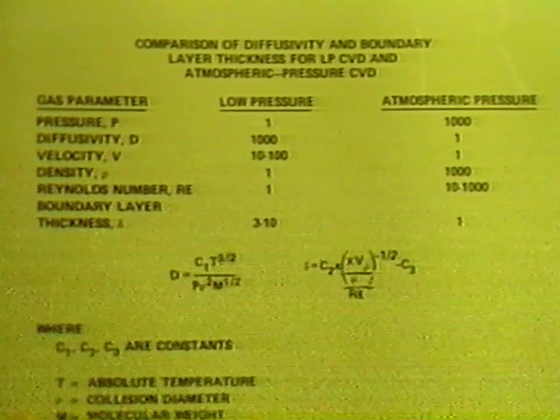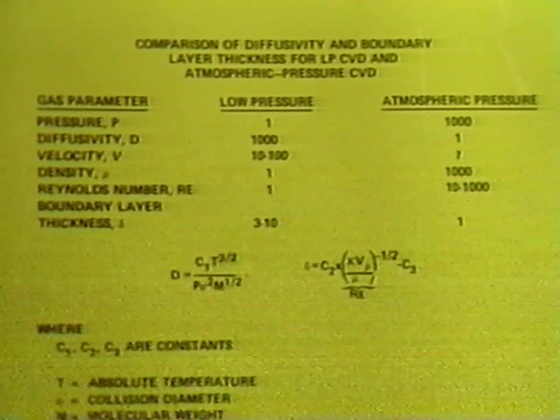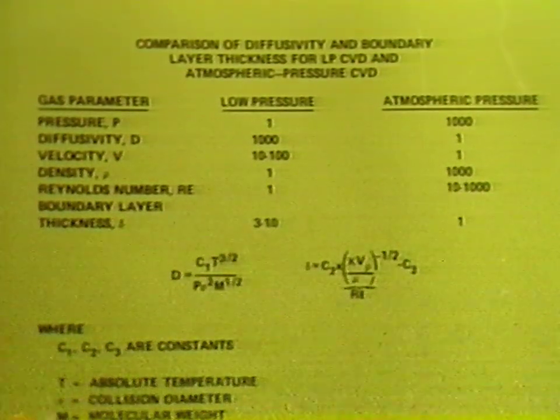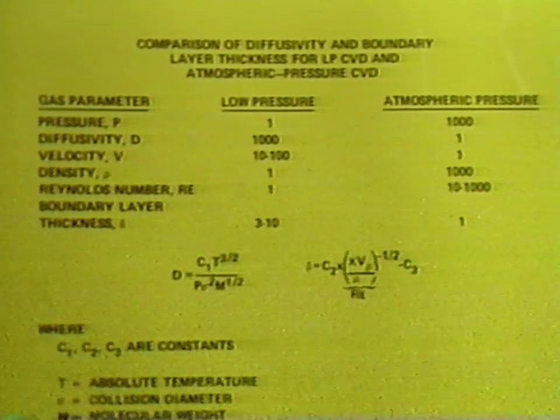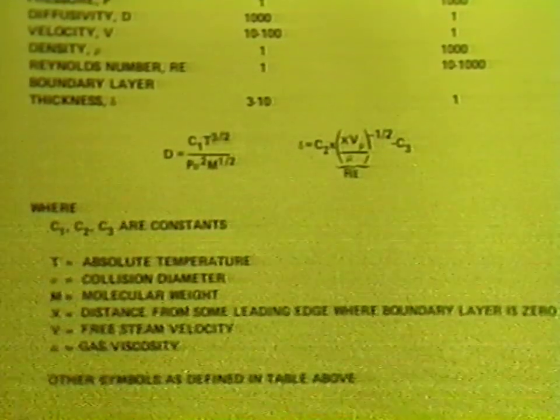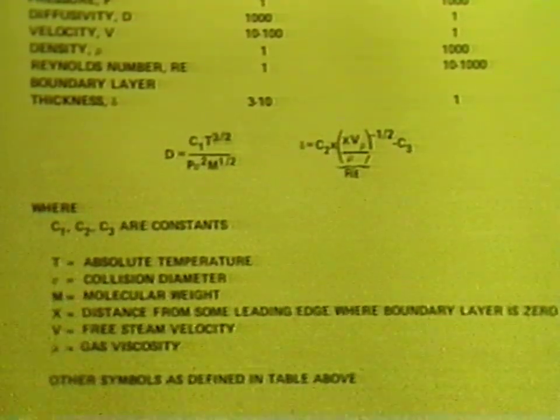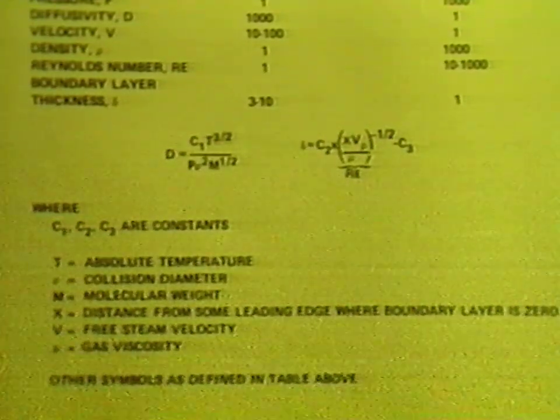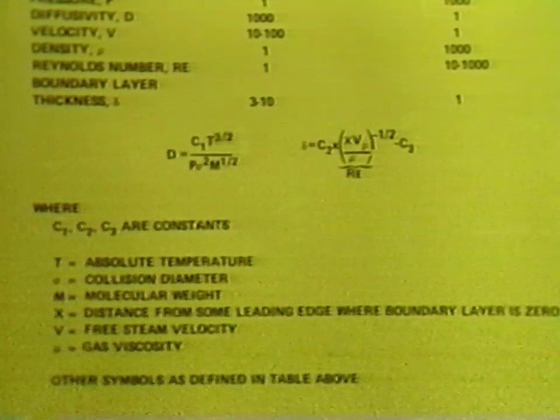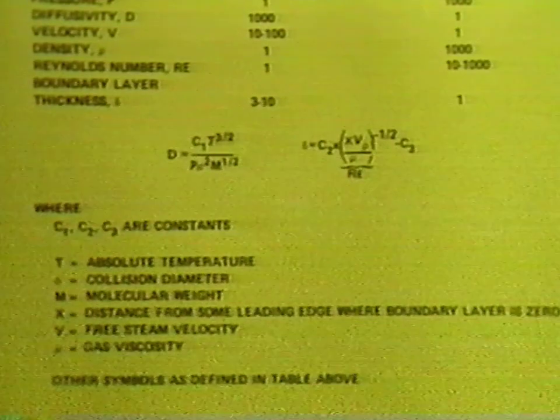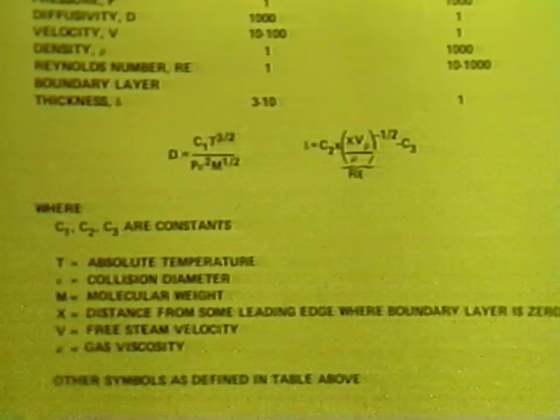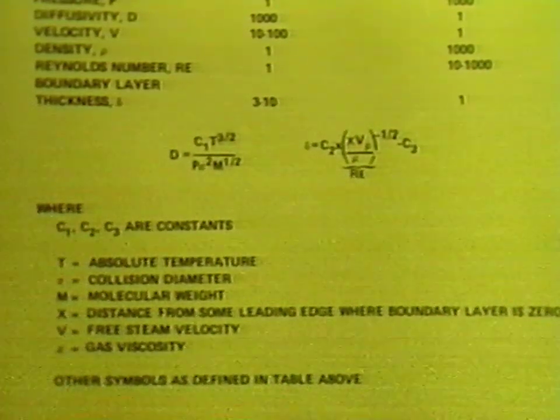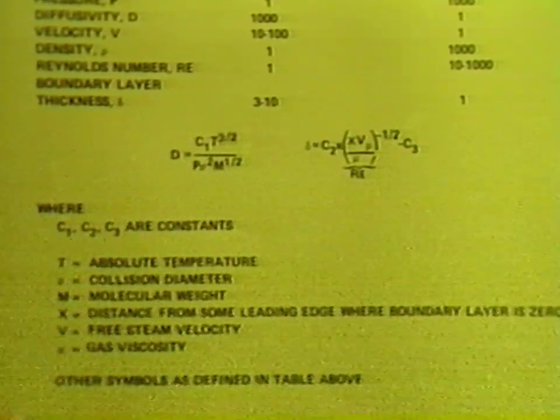And we can also see the thickness of the boundary layer changing from a value of, say, 1 to a value of 3 to 10. In other words, the thickness of the layer actually increases because the boundary layer, the stagnant layer, becomes diluted out. So you have an expansion of that layer. However, the diffusivity changes to a very large extent because the diffusivity through that layer, because it is expanded, is greatly different from what we have under atmospheric pressure conditions for the various gas species. And of course, the boundary layer thickness is defined in this equation over here, where the Reynolds number is part of the expression. The terms are detailed down here to specify exactly what is meant by the various terms.